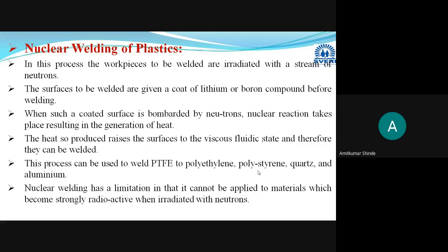Okay, if the flow of neutrons is in a larger quantity, then it will increase the brittleness of that particular plastic material, so that flow should be properly controlled. That is one of the limitations of this process.